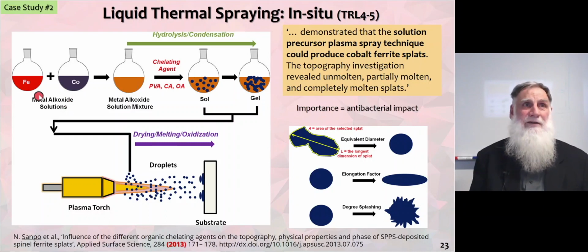are literally combining solutions, metal alkoxide solutions, with various chelating agents of PVA, citric acid, oxalic acid, forming sols and gels, and these are sprayed directly into a plasma torch. This is groundbreaking work by Sanpo et al. in about 2013. Now, the purpose of this work was to look at the splats which are so formed, and then by analysing the splats, come to an understanding about the degree of melting and how an integral coating is built up.